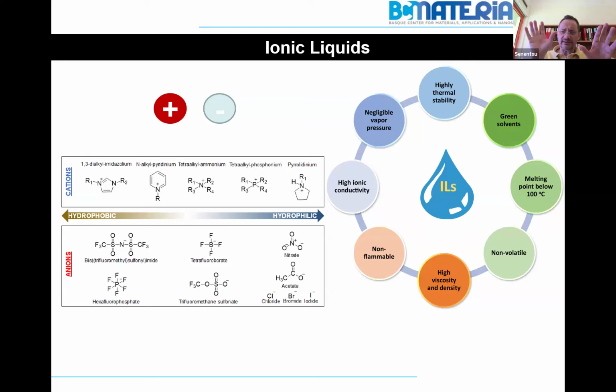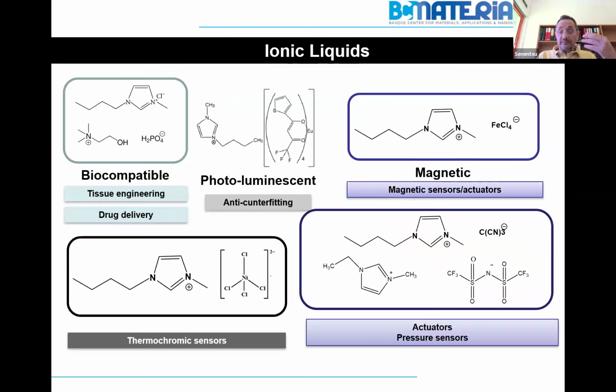And by tuning the anions and cations, you can tune the functional response, but more important, the interaction with the solvent, if you use one, or the interaction with the polymer. That means the stability of the functional ink and the rheology of the functional ink. And for example, here, biocompatible anions and cations for tissue engineering, photoluminescence for anti-counterfeiting, magnetic anions for magnetic sensors, more conductive ionic liquids for actuators and pressure, or also magnetic in this way, but with thermochromic properties.